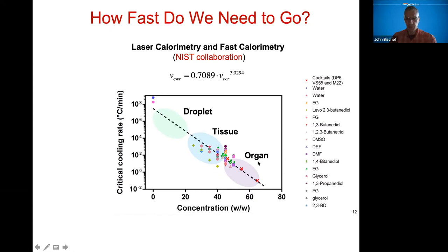And the heat transfer, basically, in an organ, we're never going to be traveling at millions of C per minute in a large centimeter scale system. So we have to use larger concentration in those systems. As we drop in scale to a tissue that might be on the millimeter or several millimeter scale, we can go into slightly lower concentration. And then finally, in droplets, we may actually get into much smaller, just a few molar concentrations. And again, the warming rates have to be orders of magnitude higher than the critical cooling rates.